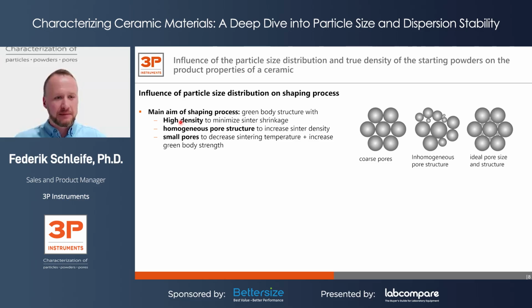Why are these three properties of the green body important? A high density is needed to minimize shrinkage during the sintering process. After the green body is formed and sintered, the sintering effect will lead to a shrinkage. If we don't have a high enough density, then you get a higher shrinkage. And this is of course not desired, as you want to keep the dimensions you gave the piece during the green body formation.